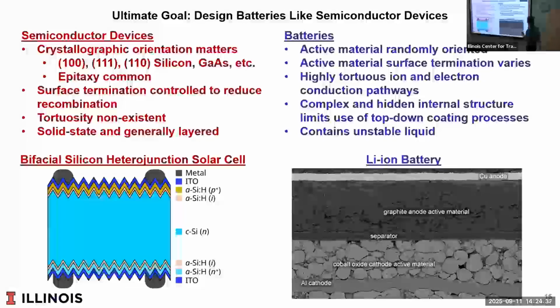Ultimately, we'd really like to think about whether we can build a battery like a semiconductor. In fact, since people here know a little bit about pavement, much more than me, obviously, if you look at a battery, the positive terminal is actually a mixture of inorganic particles, carbon black, and basically tar. So a positive battery terminal has a similar morphology to some granular media. It's made up of ceramic particles, conductive material, and a glue, an adhesive, which is usually just a pitch-based adhesive. And the problem is that there are a lot of spaces here where nothing useful is happening. If I'm a lithium or an electron, I have to go through some really complicated pathway, lots of surfaces.